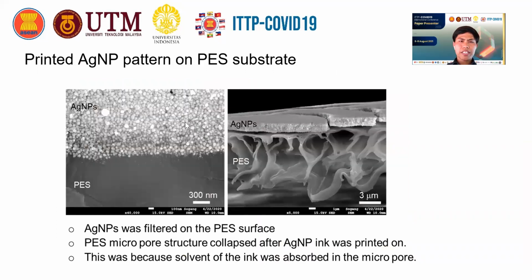After printing, we look at the particles, which are totally filtered on the surface. I mean, we make a highly connected silver nanoparticle pattern on the surface without penetrating into the porous structure inside. So it means that it works just perfectly. It filters the nanoparticles on the surface and lets the solvent penetrate into the matrix. And we want to make great lines with higher electrical conductivity.